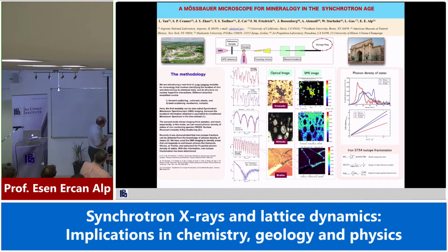Then you look at the Mössbauer spectrum in the time domain. From these peaks, I can tell what the magnetic field strength is. And from that, I can say whether it's an iron-nickel alloy, and if it is, how much nickel is in there. If it is a troilite, like an iron sulfide, I can identify that because each one has a very unique signature. A non-magnetic phase like olivine or pyroxene will also tell me something. Something like hematite tells me that there has been change since the meteorite fell on Earth. So I have done all of that.